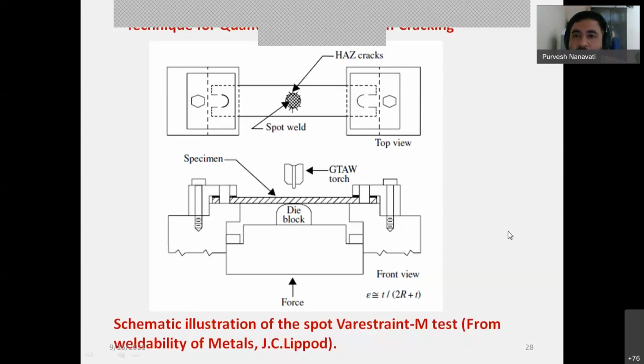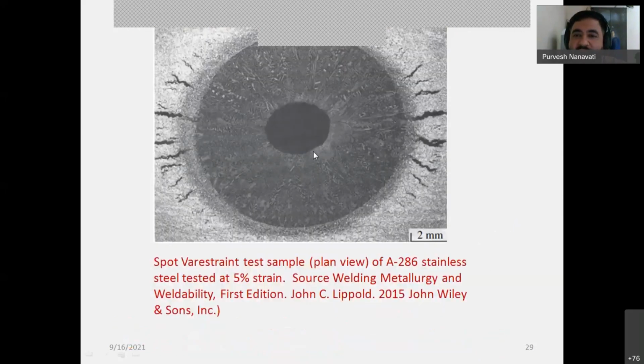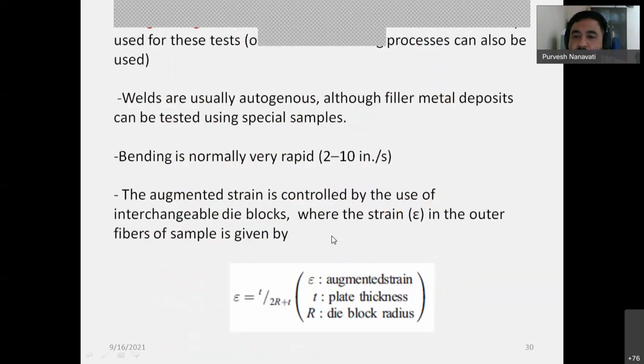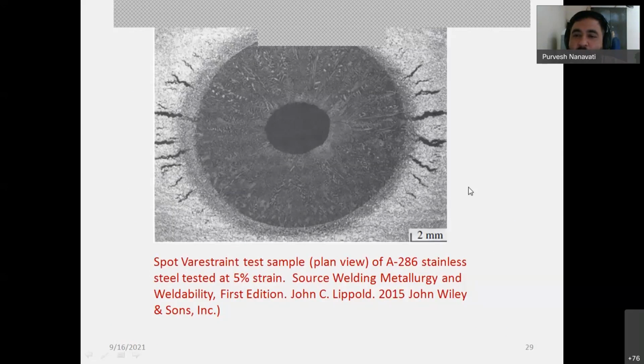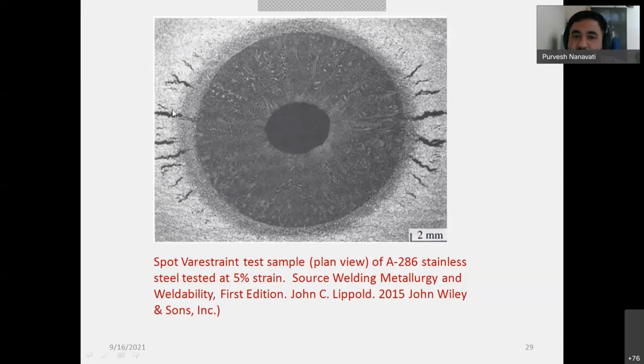So now you see this is a picture from the same book. It is a A-286 stainless steel at 5% strain. The strain is also calculated here. At a 5% strain, you would literally see a crack in the heat affected zone, right? This is a HAZ, and this is a spot.